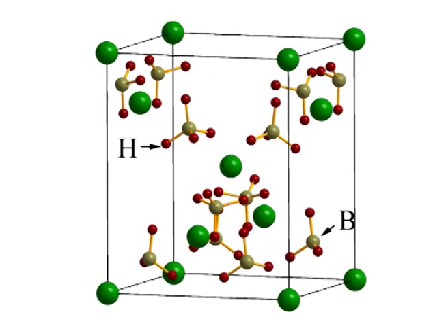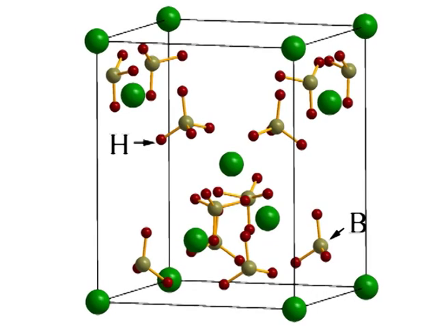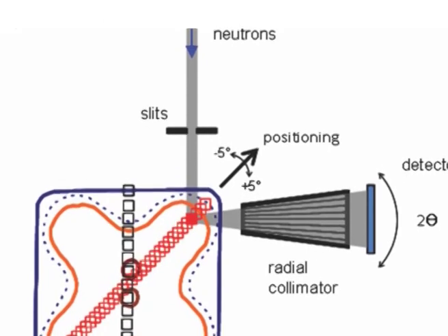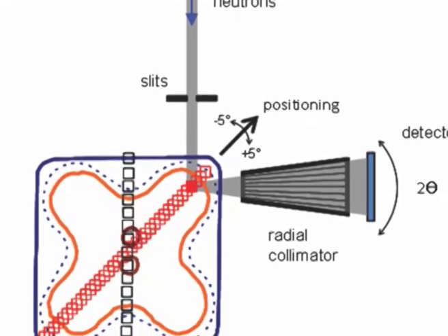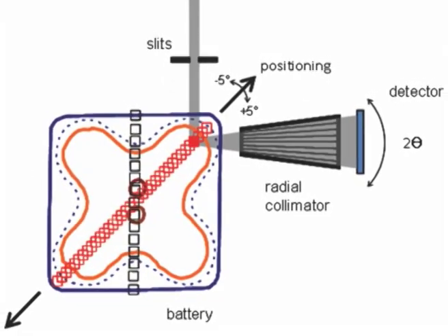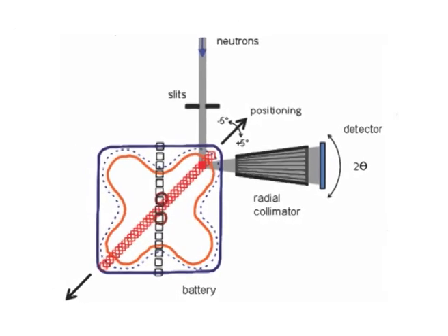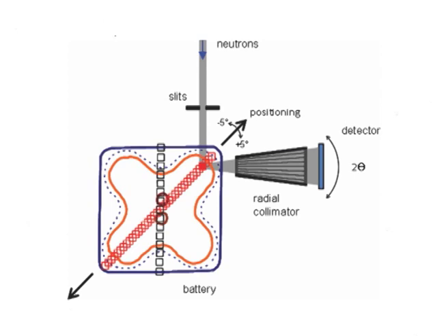If the location of the hydrogen atom is of specific interest, for example in the study of hydride structures and hydrogen bonding interactions, use has to be made of the much more expensive and less available technique of neutron diffraction. The theory of neutron diffraction is very similar to that for X-ray diffraction, but an essential difference is that hydrogen atoms scatter neutrons as effectively as many other atoms, and for this reason they can be located with good accuracy in the structure determination.